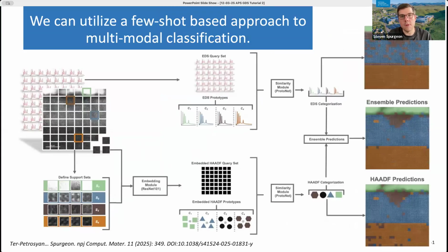So the way that we approach it is we basically analyze multiple channels of imaging and spectroscopic data simultaneously. In this case, we're using a few-shot-based approach where we're going to select examples of known regions to classify the unknown regions in this image. But basically, every pixel in our high-angle annular dark field image has a corresponding energy dispersive X-ray spectrum associated with it. We then perform classifications on the basis of just the EDS data, just the HAADF or the imaging data, and then we ensemble the two and we average the prediction of the two.